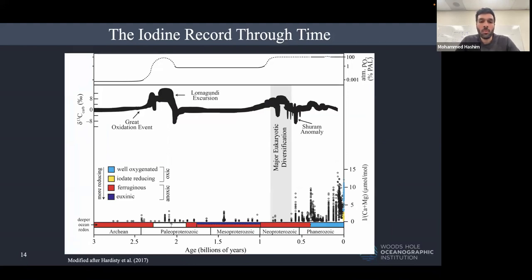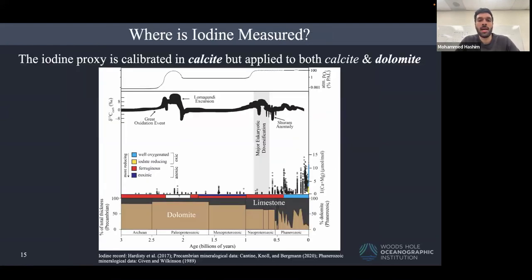In general, there was little iodine in the Precambrian. There are some peaks here and there, but then iodine increased after this second event, the Neoproterozoic oxidation event, when the oxygen was high. And so the idea here is that this is in general agreement with our understanding of oxygenation. The important part here is that most of the carbonate rock record is comprised of dolomite, as you can see here from this plot.